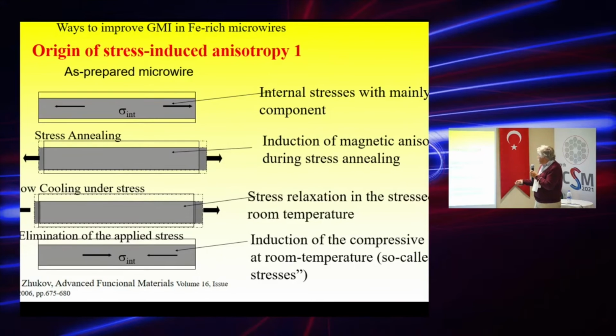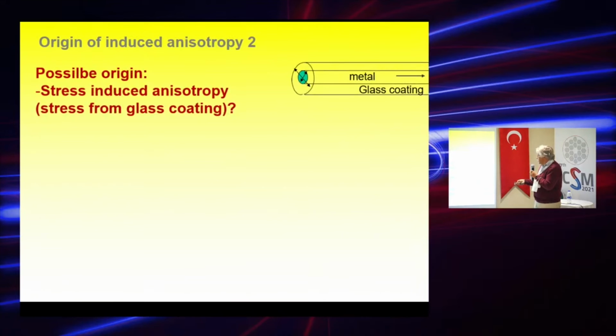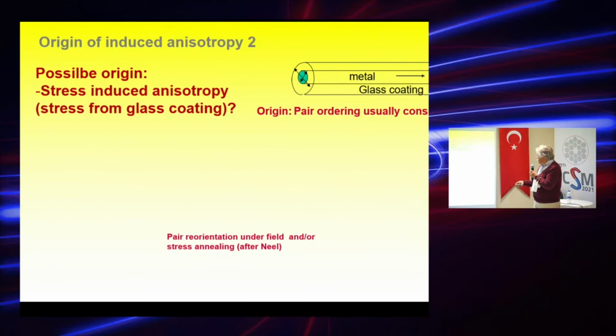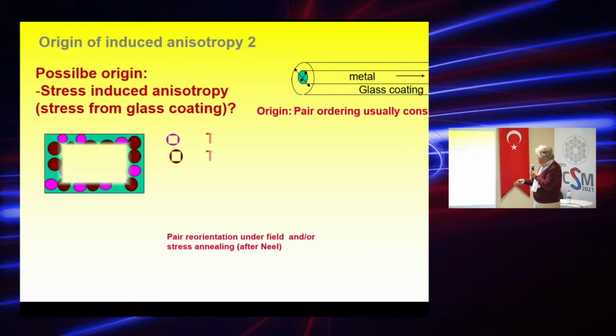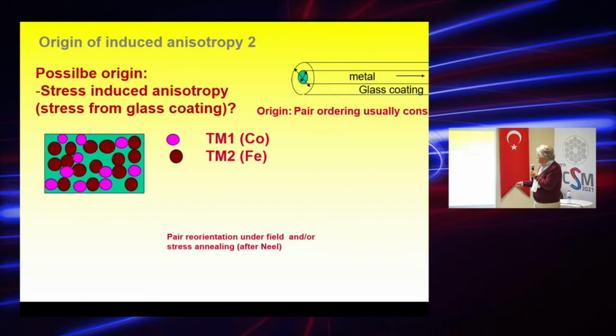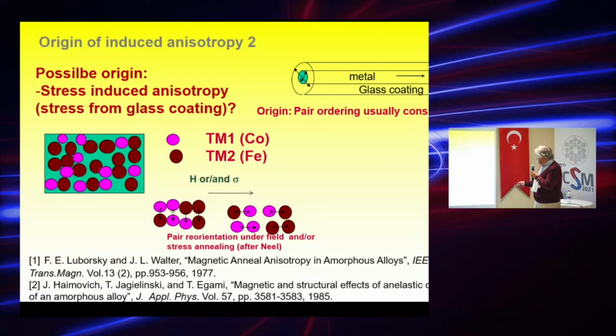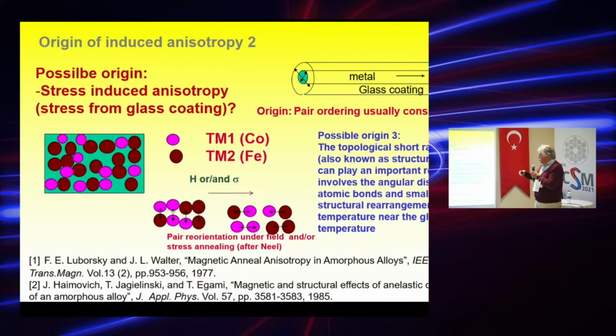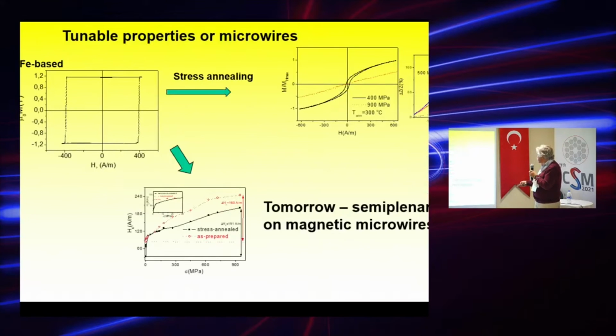I already mentioned that one of the origins is back stresses. In this case, on stress annealing, we create compressive stresses, and these stresses compensate the originally axial stresses inside the materials. But there are different models of this kind of stress-induced anisotropy. For example, one of these is orientation of magnetic pairs, so-called pair ordering. In our case, we have only one material, therefore this origin hardly applies. The other one is just a change of topology at the level of local structure, which produces this kind of stress annealing induced anisotropy in these materials.